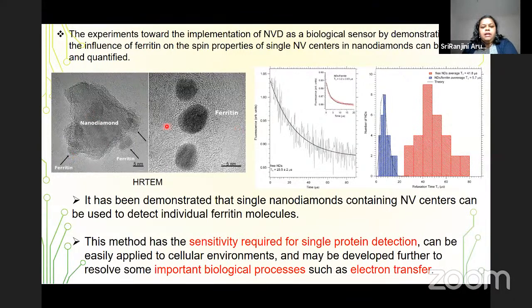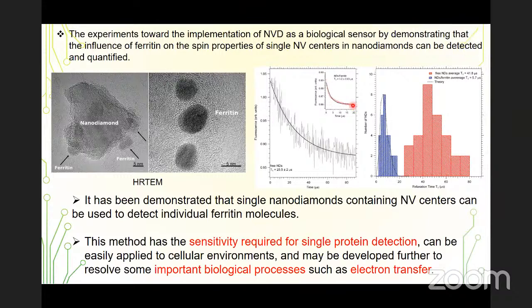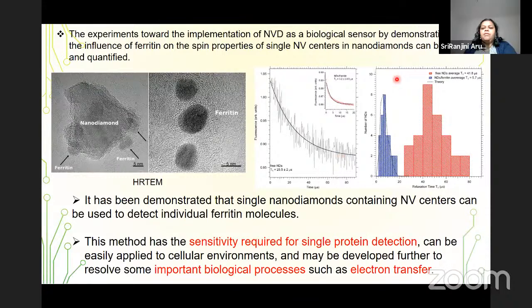So here we have the system of ferritin with the incorporated nanodiamond, looking into the fluorescent decay. This is a typical picture of the T1 relaxation time, both for the nanodiamonds with ferritin and the nanodiamond itself, the free diamond. We can do a histogram of a single protein in this case. This is the free nanodiamonds, with an average T1 relaxation of 41.8 microseconds, whereas this is the one incorporated with the protein, about 5.7.